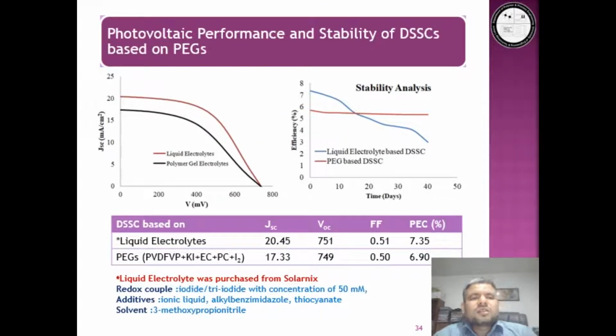Similarly, the photovoltaic performance and stability of DSSC. If you see the table, this table shows that the conventional DSSC or liquid electrolyte based DSSC possess higher efficiency as compared to polymer gel electrolyte based DSSC. But it can also be seen in the figure B that the efficiency of the conventional DSSC decreases with the passage of time. However, the performance of polymer gel electrolyte based DSSC remains stable after 40 days. So this is the major advantage of polymer based electrolytes.